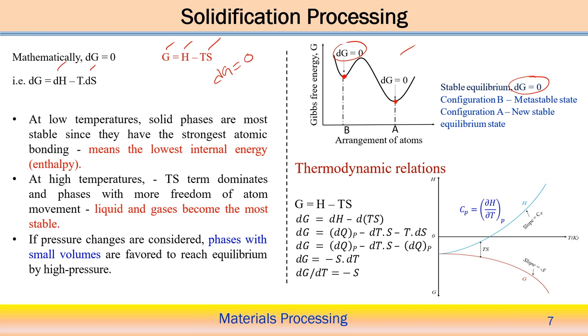But how can we utilize this to explain the stability of the different phases? At low temperature, the solid phases are more stable because they have the strongest atomic bonds. Solid phases having the strongest atomic bonds are stable at the lowest temperatures. This means the lowest internal energy of the system, so dH should be low. At low temperature, the main driving force to bring stability to a system is basically low values of the enthalpy.